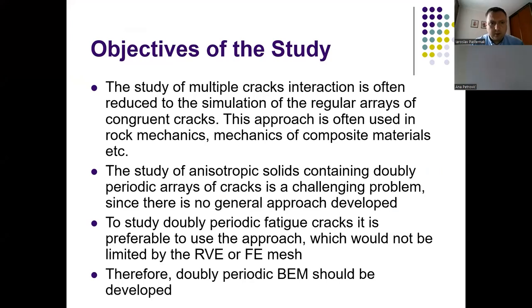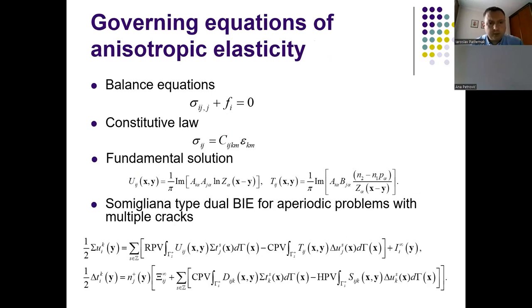We have developed two different models. The first model is based on the doubly periodic representation of cracks, and the second model is based on the non-periodic analysis of the problem. We used boundary element method to derive the solution because it won't have an analytic solution, and the boundary element method allows us to study crack growth.